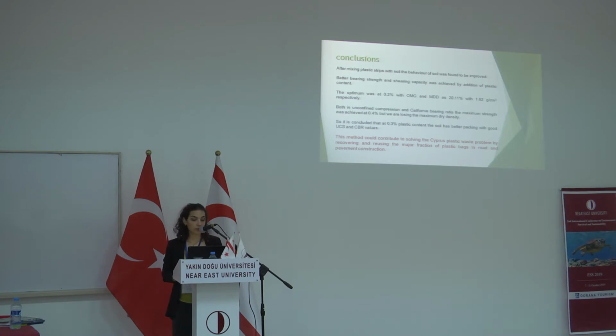Both in unconfined compression and California bearing ratio, the maximum strength was achieved at 0.4%, but we are losing maximum dry density from 0.3 to 0.4. So it is concluded that at 0.3% plastic content, the soil has better packing with good unconfined compression strength and CBR values. So this method could contribute to solving the Cyprus plastic waste problem by recovering and reusing the major fraction of plastic bags in road and pavement construction.